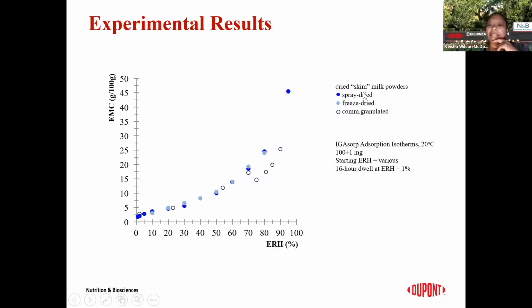In terms of comparing the spray dried and the freeze dried powders, again, you see that same type 2 sigmoid shape that we saw previously, and in the characterization of the isotherm forms that I showed earlier in the chart. One thing that we did not see with our powders was this discontinuity. We took the time to purchase some commercial granulated milk from the grocery store to see if we could see this discontinuity.